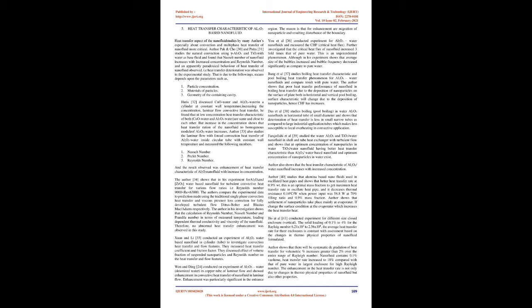Author 34 shows in his experiment for Al2O3 and ZrO2 water-based nanofluid, for turbulent convective heat transfer at various flow ratios, i.e., Reynolds number 9000 to 63000, the authors compared experimental data to predictions made using traditional single-phase convection heat transfer and viscous pressure loss correction for fully developed turbulent flow, Dittus-Boelter and Blasius-McAdams respectively. The author's investigation shows calculation of Reynolds number, Nusselt number, and Prandtl number in terms of measured temperature, loading-dependent thermal conductivity and viscosity of the nanofluid. Therefore, no abnormal heat transfer enhancement was observed in this study.